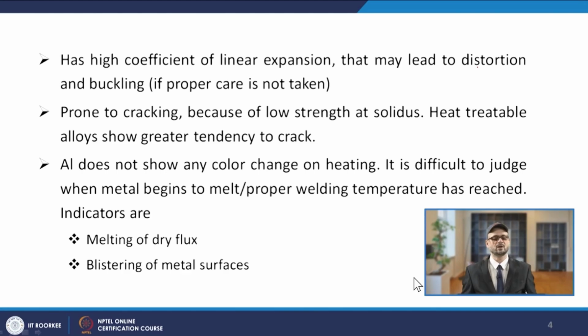Aluminum does not show any color change on heating. It is difficult to judge when the metal begins to melt and the proper welding temperature has been reached. Indicators are melting of the dry flux and blistering of the metal surfaces.